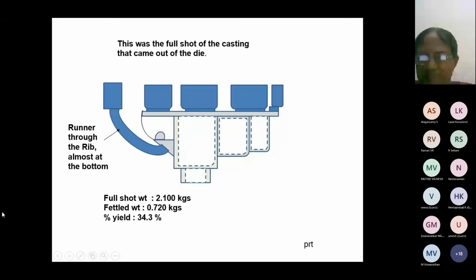And this is the casting that came out of this die. This is formed by the bottom core, this is the top core. The entire thing is the top core. See how many runners go through the rib: 1, 2, 3, again 3 on that side is 6, plus 1, 7 runners are to be fettled. The full shot weight was only 2 kg and the fettle weight is 0.72 kg and the yield is as low as 34.3%. And we require 2 operators to operate this die. So management is not very happy. We have to make improvements.